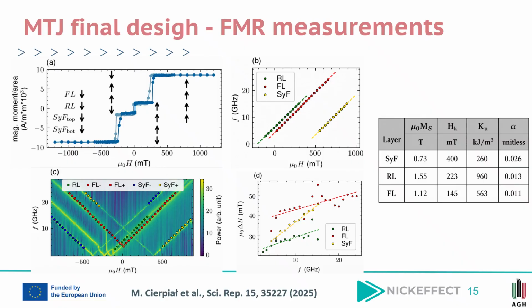The effective magnetization, anisotropy field, anisotropy energy, and damping parameter are summarized in the table on the right side of the slide. The optimized free layer exhibits low damping together with strong perpendicular anisotropy, which are desirable for low current and high-speed STT switching. At the same time, the SyF and RL systems remain strongly stabilized, supporting reliable operation of the complete MTJ structure.